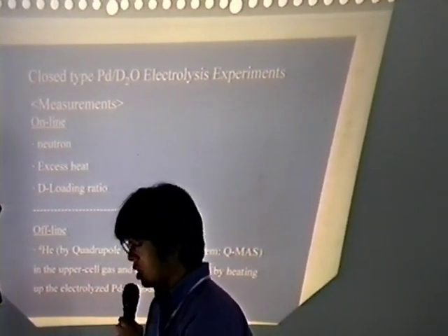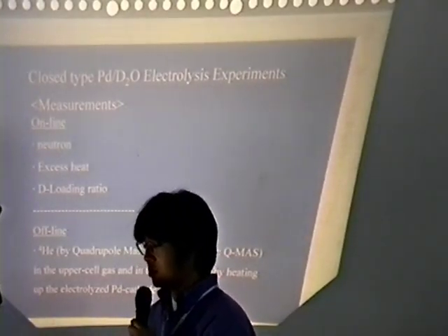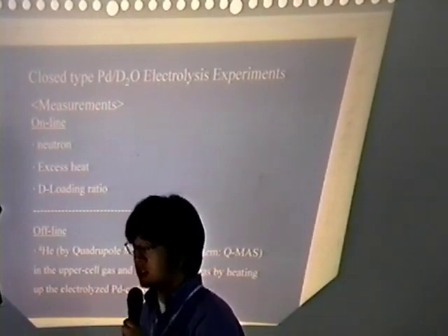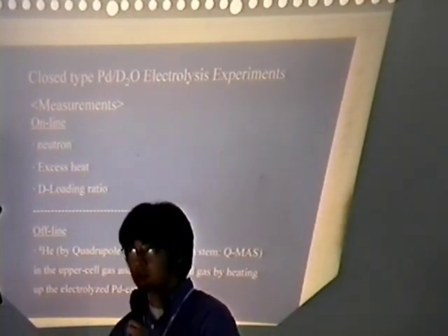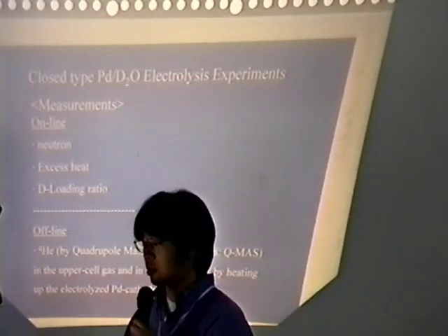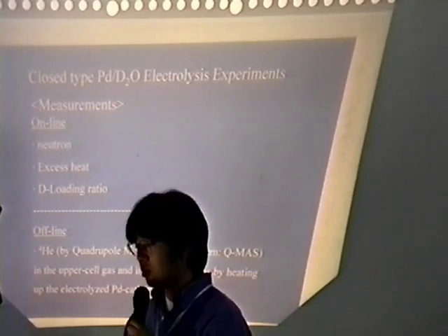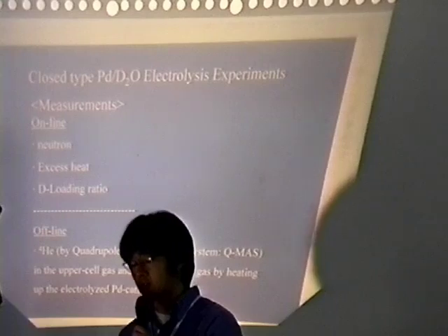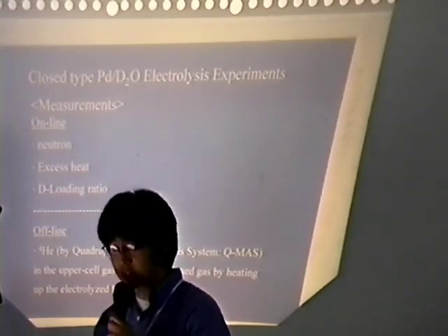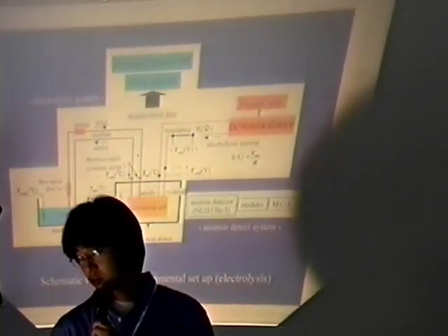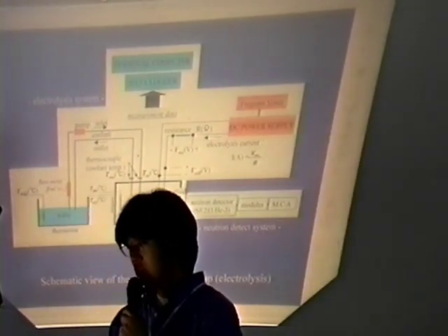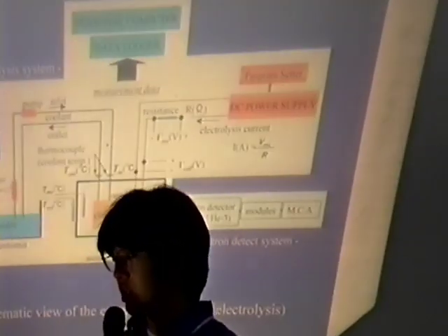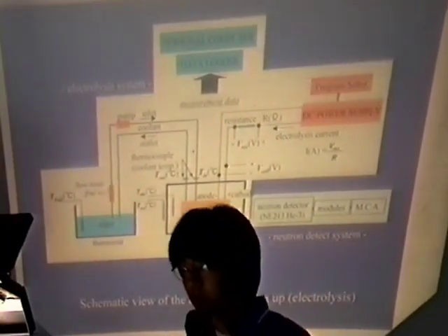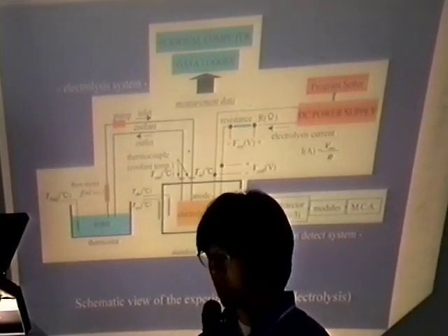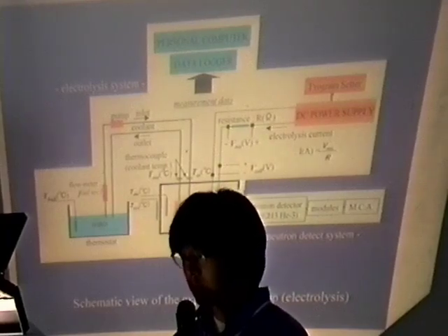was performed during the electrolysis. And after the electrolysis, helium-4 detection was tried for the upper cell gas, and since there is a possibility that generated helium-4 was accumulated in the palladium cathode, the electrolyzed cathode was heated up after the electrolysis, and the released gas was also analyzed. This figure shows the schematic view of the experimental setup. Neutron detection was performed with an NE213 scintillation detector or helium-3 gas detector. Heat measurement was performed using the mass flow calorimetry method.